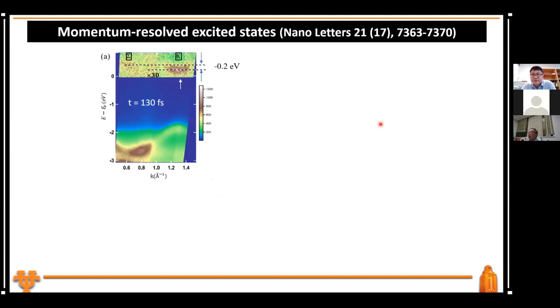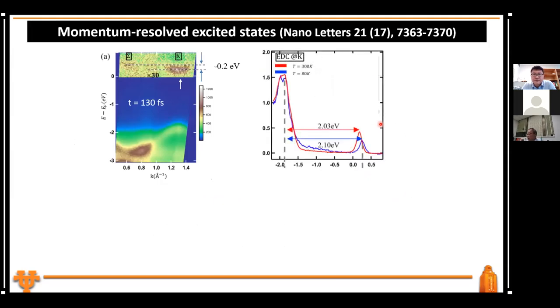And I won't go into the detail, just try to tell you that indeed we achieve this, and then we measure the quasi-particle tunneling gap. This is where the valence band maxima location is, and this is the conduction band minimum location. And you can see the temperature dependence, and at 80 Kelvin, we measure the gap about 2.1 eV. Remember I indicated our first measurement using tunneling spectroscopy is about 2.15. I would say within the experimental error, the two are very consistent.